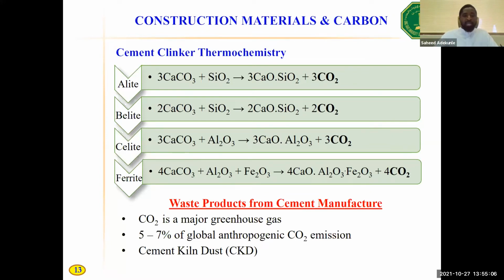In other words, we can approximate the CO2 coming out of cement manufacture, considering the energy consumption and the CO2 formation in the production itself. So one ton of cement produced gives one ton of CO2 released into the atmosphere, if not captured, okay? And therefore, 5 to 7% of global anthropogenic CO2 emission comes from the manufacture of cement and related activities.